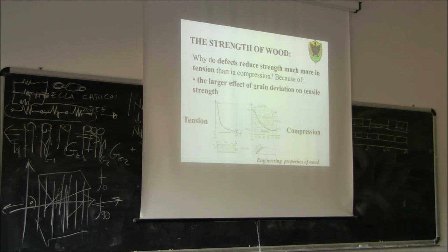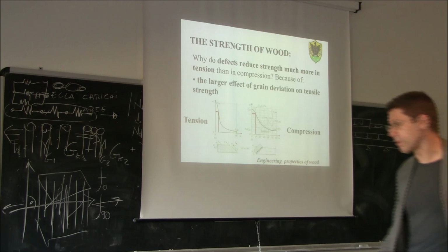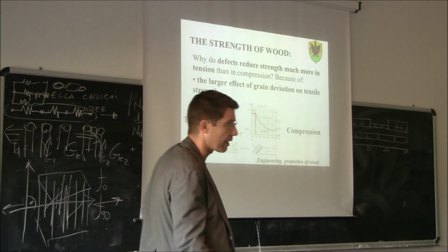What does it mean? It means that even with a very small value of grain deviation, let's say 10 degrees, you can see we have a drop of tensile strength of almost 30%. While instead, for compression, the reduction is much lower. This means that the grain deviation affects tensile strength more than compression strength. That's the first reason.